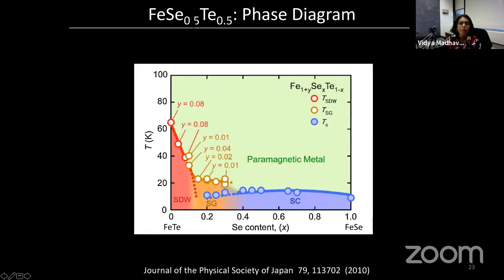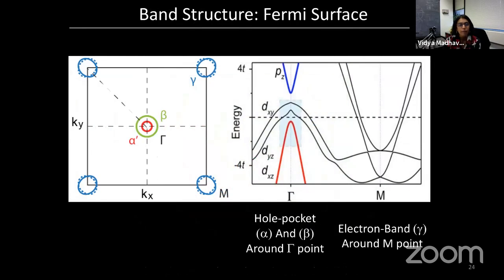So the phase diagram of FeSeTe looks like this. One end member is actually a spin density wave state. The other side is a superconductor. And it is for this very narrow range of compositions close to 50-50. I'm not sure how broad this is, but for this composition close to 50-50, you should see band inversion, and this material should be topologically non-trivial.